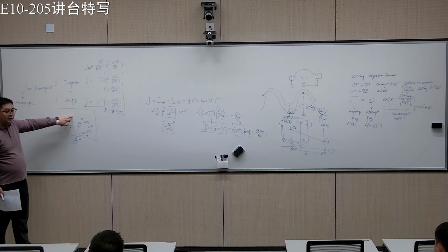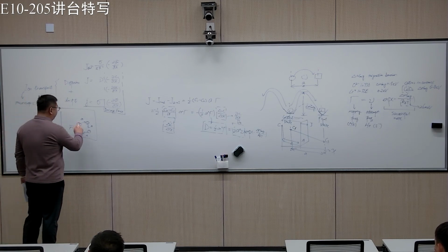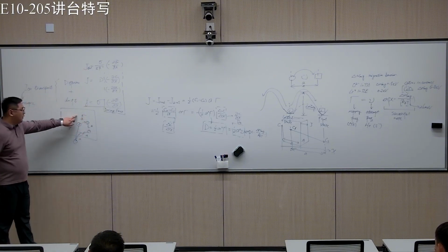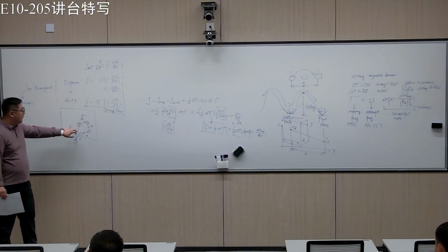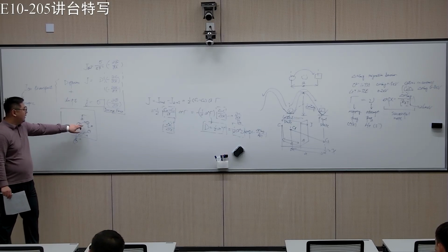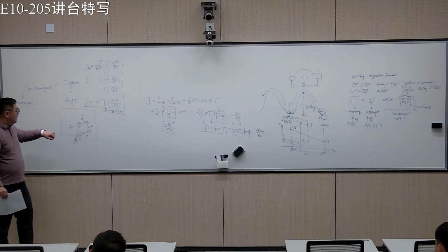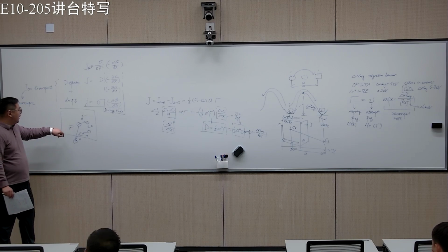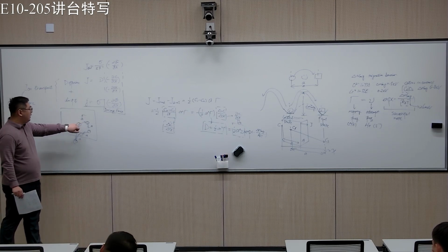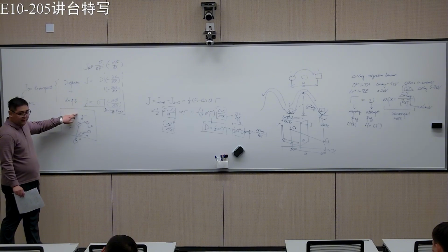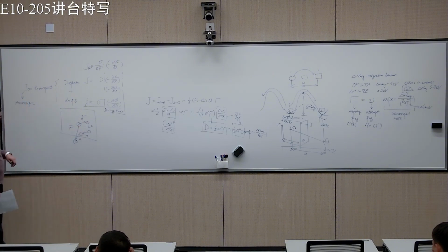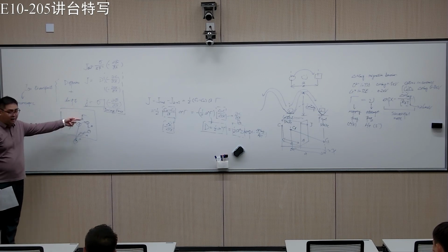So from 1 to 2, you have the successful rate, or the hopping rate, which is gamma, determined from this position to that position. Now finally, if you measure on average how far an ion has diffused, it has a correlation both to the success rate, basically the hopping frequency, and also to how far the ions can hop in each case.